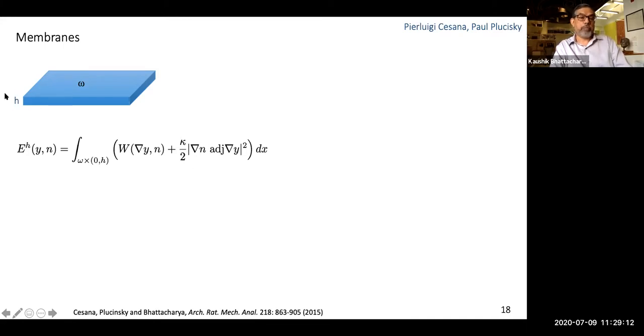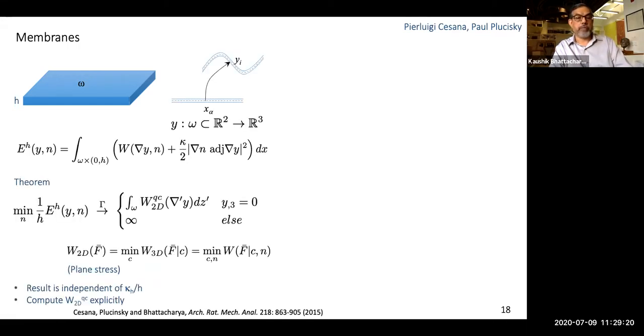But you have two small parameters. You have the thickness, but you also have this kappa, which is a small parameter. So you try to do asymptotics using gamma convergence when both of these go to 0. And you find that in the gamma limit, the effective energy behavior is described by the 2D theory, where the 2D energy, so all that matters is the deformation of the midplane.